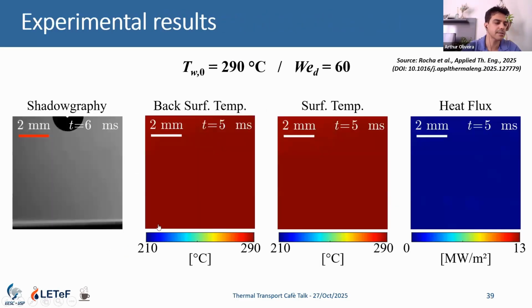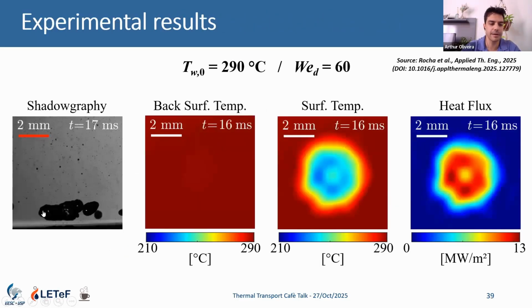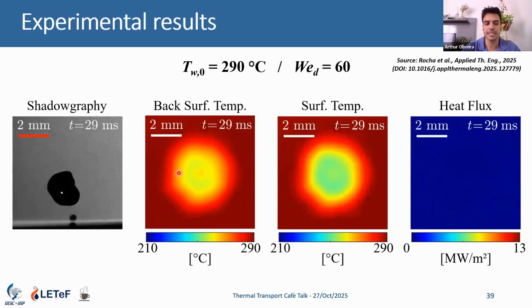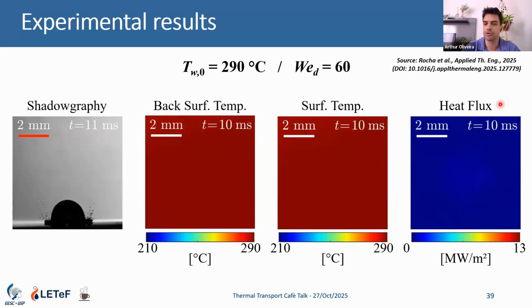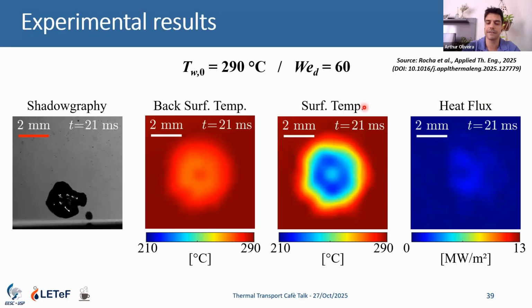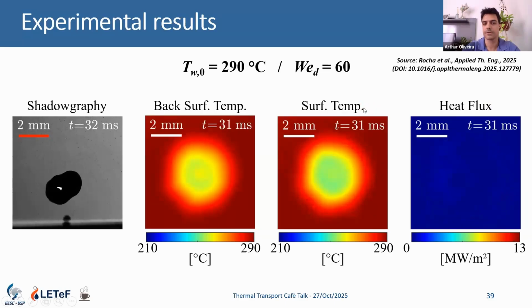So here you can see the results. We have the shadowgraph here, very nice images. This is the infrared thermography images. And this is what I showed you, the estimates from the heat inverse method: the heat flux evolution over time and the impacted surface temperature evolution over time.